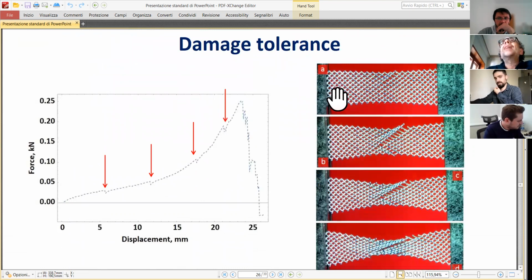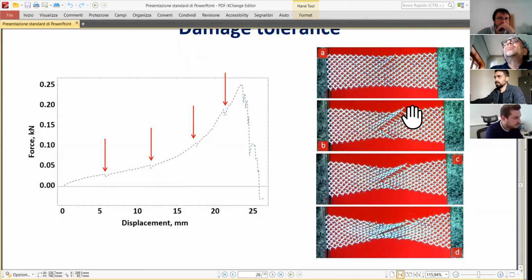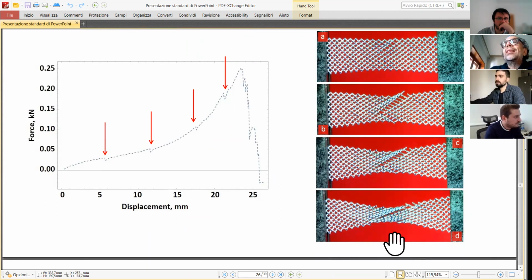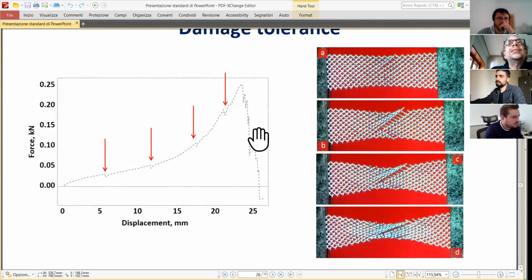These specimens are damage tolerant. This is a specimen which, for a reason which we could not understand, has been printed with some small defects, okay? So while testing it, we had some jumps in the plot of displacement versus overall force. By the way, we are talking about 100, 200 newtons. So it is rather stiff for such a light specimen, okay? So what happens? One beam is broken, but it keeps doing its job. So we are optimistic that this microstructure produces a damage-tolerant metamaterial.